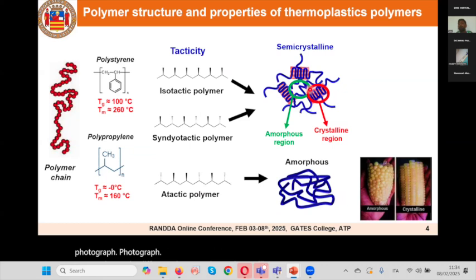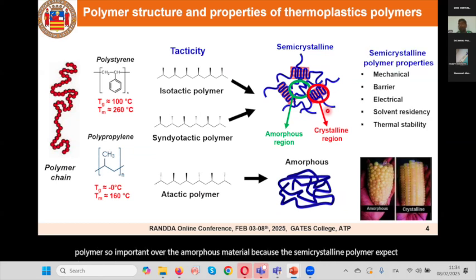Why is semi-crystalline polymer so important over the amorphous material? Because the semi-crystalline polymer exhibits extraordinary physical properties like good mechanical properties, barrier property, electrical properties, solvent resistivity, and very good thermal property compared to the amorphous polymer. This is because the crystalline phase acts as a pillar that improves the overall property of the polymer. Because of this, the semi-crystalline polymer shows extraordinary physical property over the amorphous polymer.